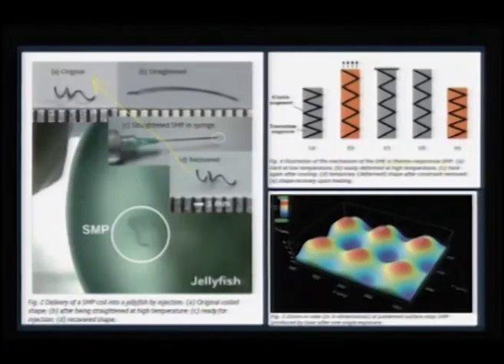As a result, you can see this is the morphology with which you start, and then when you heat it, you can stretch this polymer along, and immediately when you cool it, it can retain this memory, and once you heat it again it can revert back to its original shape. So it has both the features in it. You can retain the memory when it is cold and you leave it there, or you can heat it again and revert it back. So this is one application.